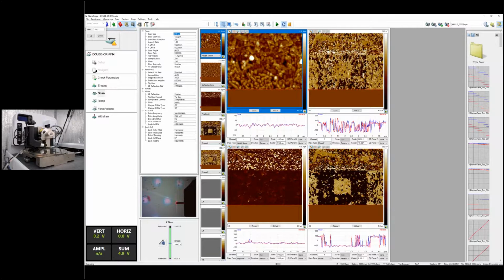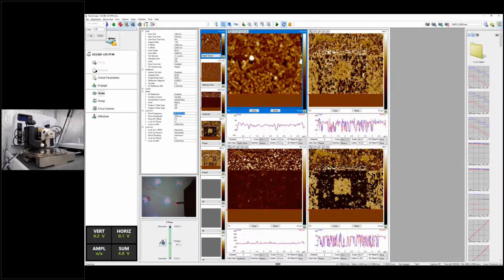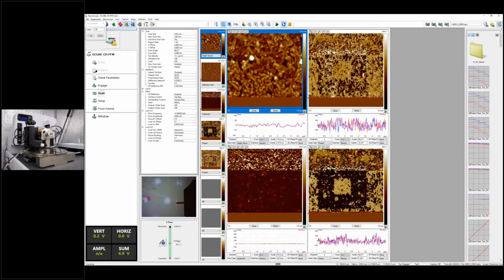And we mentioned earlier that the piezo response can quite often be very weak. So we use different methods to try to boost the signal. The AC modulation is one way, and it's the most common way to do it. Now I'm going to change the frequency for this AC, and then you will observe the difference here. You can directly see that the amplitude channel gets much lower. That's because I changed from a higher frequency, relatively close to the contact resonance frequency between this tip and sample, to an off-resonance frequency, which for now is 15 kilohertz.